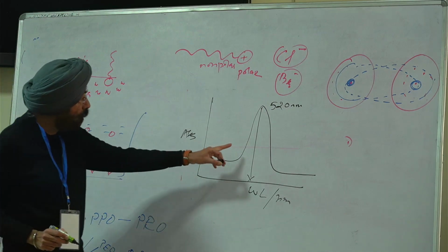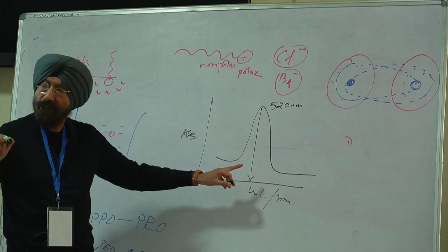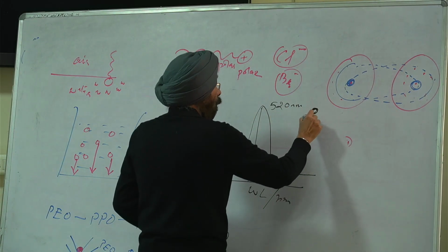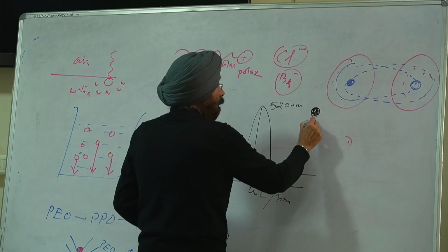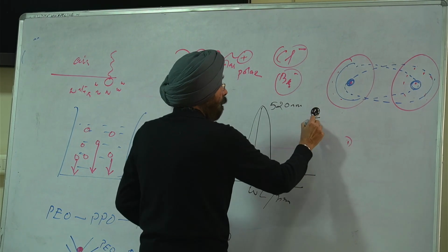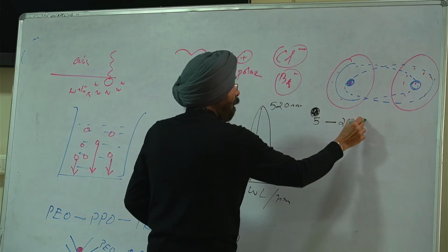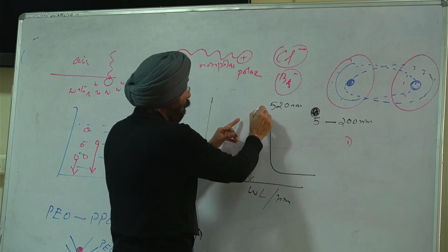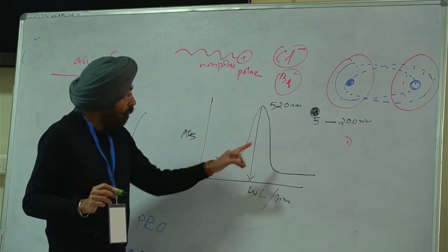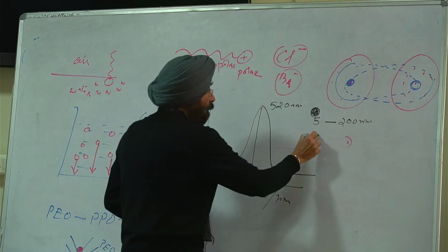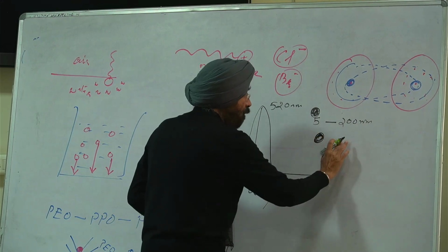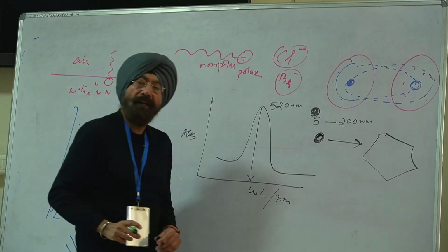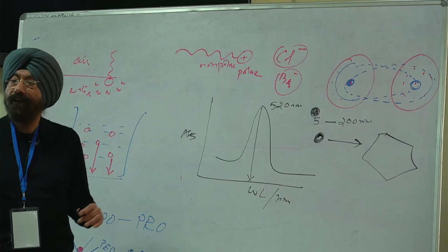If you have the absorbance of that red color solution close to this, it means that you have polyhedral nanoparticles with dimensions anywhere from 5 to 200 nanometers, right? If this absorbance gets broader, the peak gets broader, it means the shape changes from sphere to something else, like a triangle or plate-like, or a bigger molecule of a different dimension.